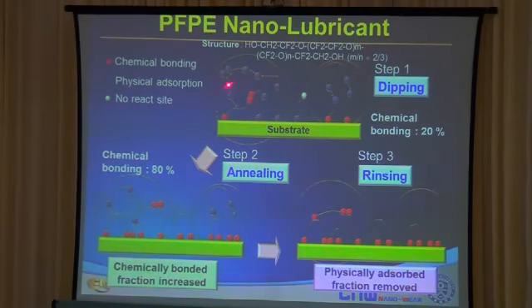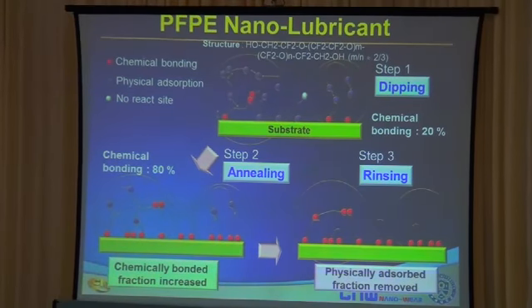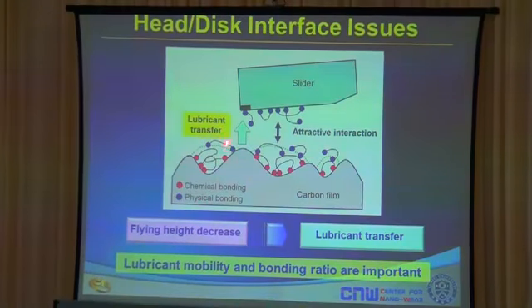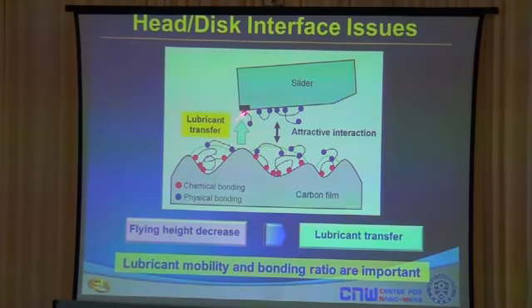You do that by the process of annealing. So by controlling the temperature and the time of annealing, you can adjust the percentage of the bonded part to the unbonded part. So I'll give you a schematic of what's going on. Here's a slider, and the head is at the tip of the slider, and you have lubricant on the surface, and during interaction you have some lubricant transfer, and this can contaminate the head and make problems in terms of signal transfer between the head and the disc.